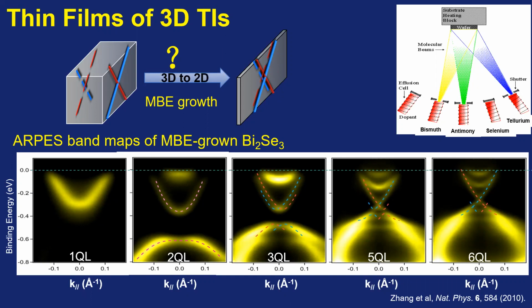So this is the ARPES data. We can see we can get the 1 quintuple layer to 6 quintuple layer. Quintuple layer means the 5 layers in the topological material. Usually 1 quintuple layer is just 1 nanometer. We can see that when the thickness is 6 quintuple layer, there is a Dirac cone.